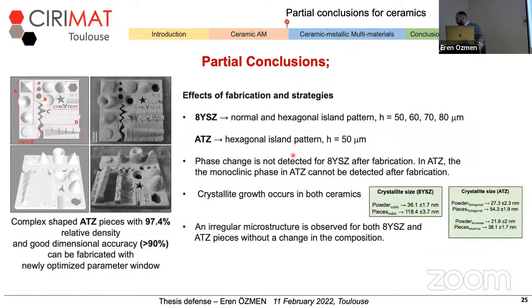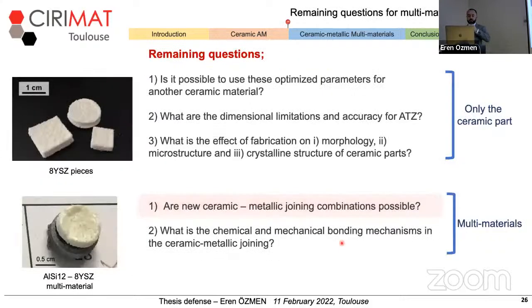So to conclude the first part for ceramics, we can say that very complex shaped ATZ pieces with very high relative density can be fabricated. And also we have a larger parameter window that works for 8YSZ based on the pattern and H distance. And also, as there is no phase change for 8YSZ, we observe the disappearing of monoclinic phase in ATZ structure, and an irregular microstructure observed for both materials without a change in their chemical composition.